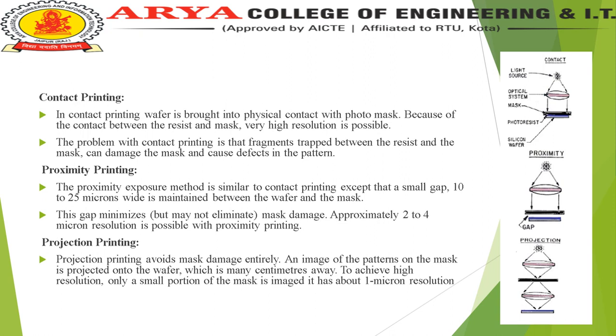Proximity printing. The proximity exposure method is similar to contact printing, except that a small gap, 10-25 microns wide, is maintained between the wafer and the mask. This gap minimizes mask damage. Approximately 2 to 4 micron resolution is possible with proximity printing.